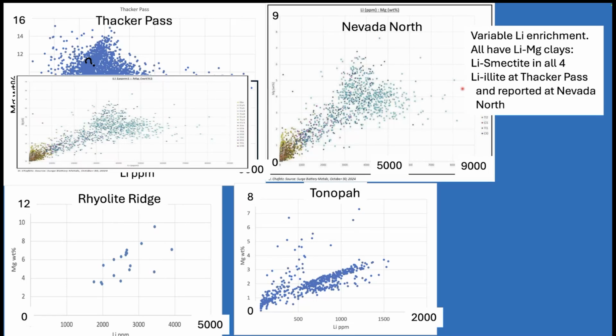An important difference, in addition to the higher lithium concentration in illite, is that smectite is a swelling clay, illite is not. And processing always uses water. If you can picture driving across a Texas farm field in clay in the middle of a rainstorm and getting stuck in mud, that's sort of the situation with lithium smectite.